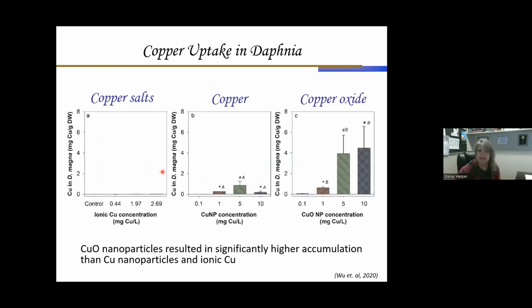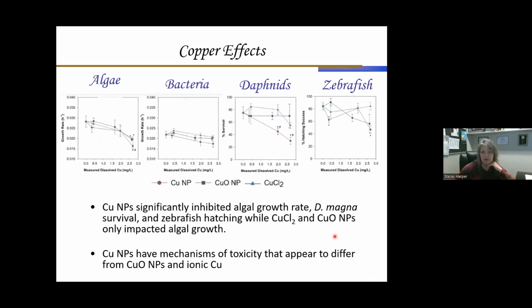But what we see is differential uptake of these particles. The copper salts are not taken up at all. But you can see here the copper oxide, and these are the copper found in Daphnia. And you can see the copper oxide nanoparticles at the higher concentrations are readily taken up by the Daphnia. And so what does this mean consequentially for them?